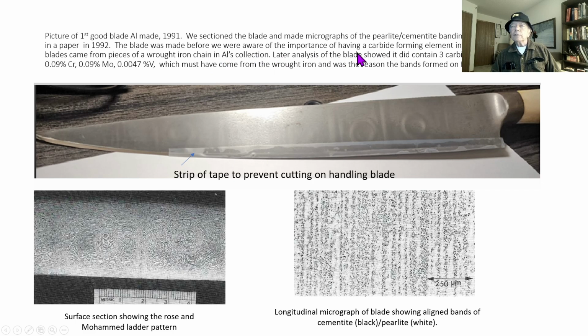Later analysis of this blade showed us that it did contain 3 carbide forming elements. Chrome, 0.09, moly, 0.09, and enough vanadium also. Well, those guys together, I'm sure, are what caused all this beautiful formation to occur when Al made the blade.